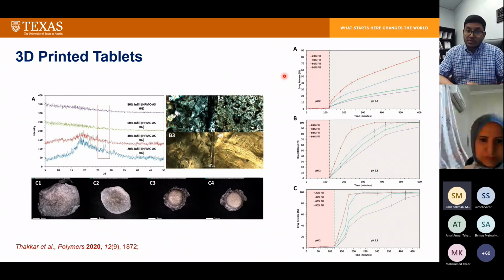And now, by only tuning the fill density, or by taking the fill density as an effective tool to control or modulate the release of the drug, we kept the drug content the same, like 20% weight by weight, and we used the same polymer in 3 different grades. We used hydroxypropyl methyl cellulose, HG, MG, and LG grade.